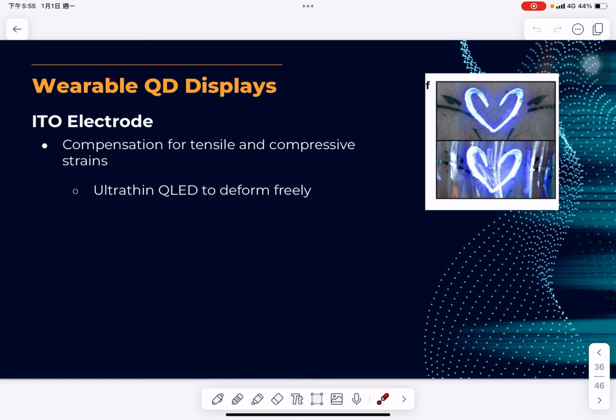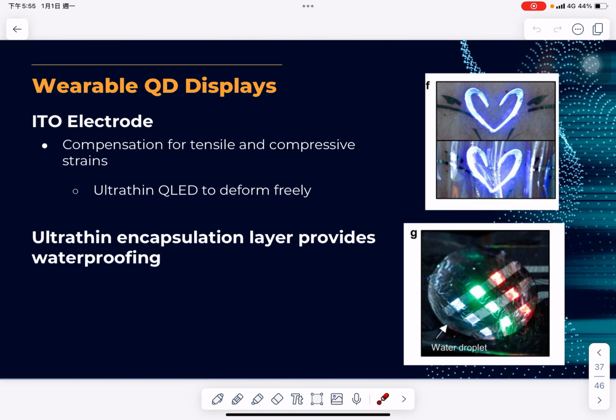Positioning the delicate ITO electrode near the neutral mechanical plane allowed the ultra-thin QLED to bend without breaking, even on soft skin. Under micro-scale bending, the flexible QLED stays below the ITO electrode's fracture limit, maintaining high flexibility. Furthermore, the ultra-thin encapsulation layer provides waterproofing, effectively safeguarding the wearable QLED in high humidity conditions.